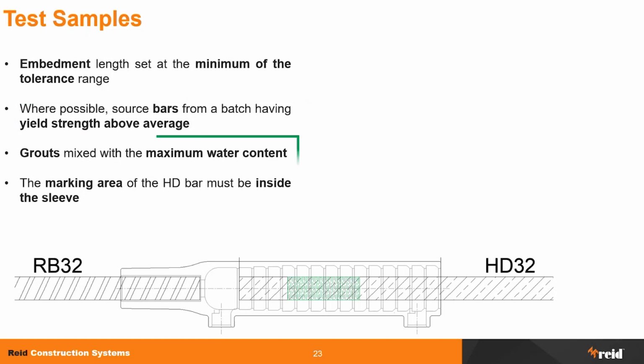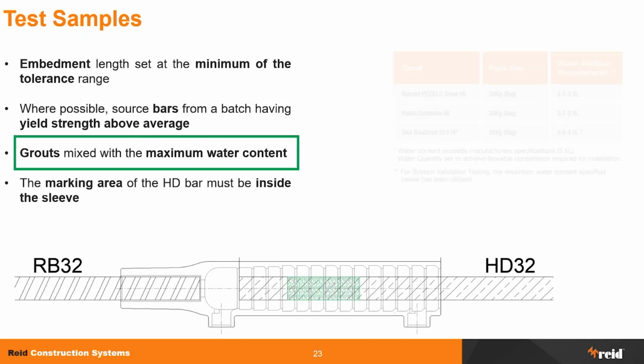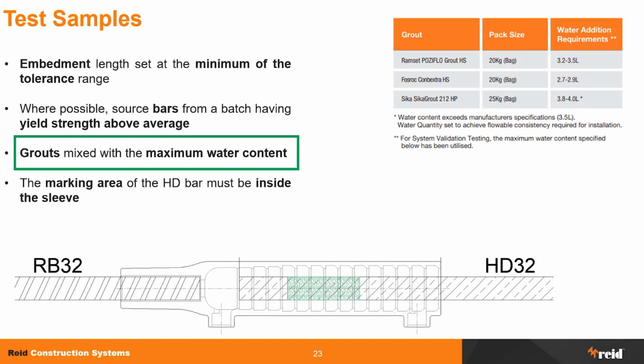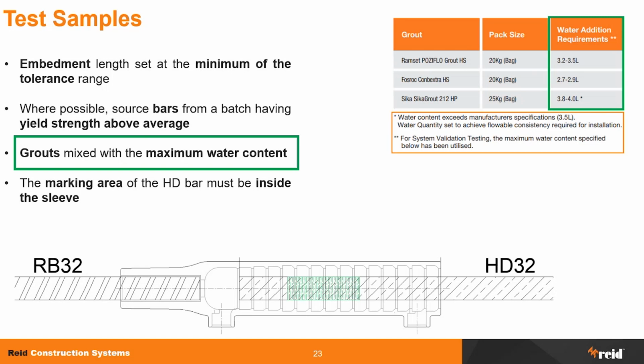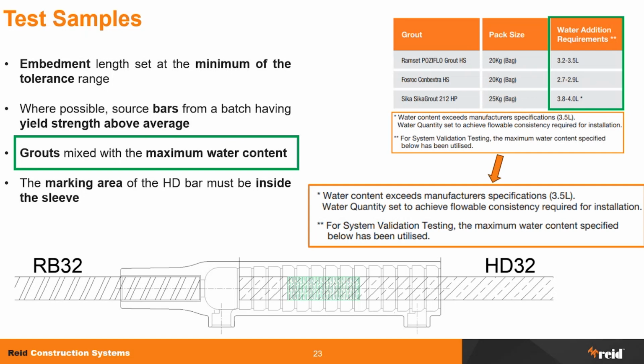Then we move on to the grouts. With these three grouts, we give a tolerance range for the water content for the mixing. And of course, we ensured that we mixed the grout with the maximum water content of the range. I would also like to point out that in one case, we actually exceeded the water content of the manufacturer, which in this case was Sika.